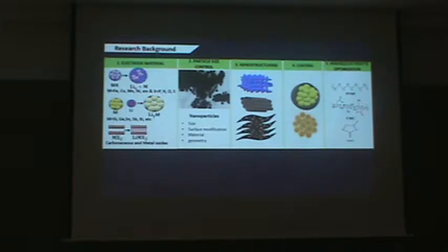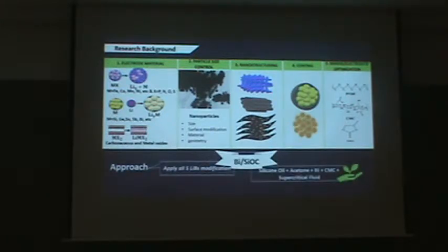And also the optimization of the binder and the electrolyte is necessary because they can help in preventing the structural morphology from collapsing. In this sense, most of the coating material or the active material is altered to solve the previous issues just mentioned. So our approach in this research is to use bismuth and silicon oxycarbide, applying all the mentioned modifications by a simple one-pot supercritical method.